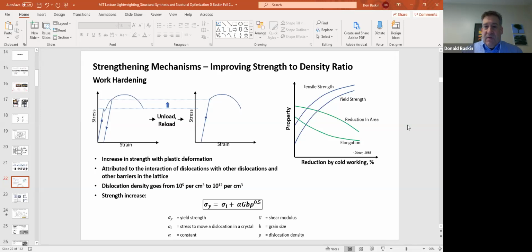Okay, and this is with plastic deformation, so you're out of the linear region at this point. If you unload at that point where you've created a little bit of plastic deformation, and then load it back up, you'll find that it takes more stress to get it to yield again. So the density of this material has stayed the same. You've put in this plastic strain. The density stayed the same, but the strength has gone up. So you really have increased the specific strength of the material, the specific yield strength. The ultimate strength hasn't changed, but the yield strength has gone up. So that's increased the strength of the material.